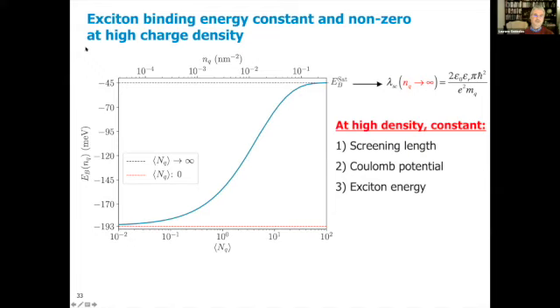And if you now calculate by solving the Schrödinger equation the exciton binding energy as a function of the number of charges in a nanosheet, you see that for a very small number of charges, or let's say when you go to zero, you get this 193, and that's what we put in here in the relative dielectric constant. And then if you increase the number of electrons and holes in a nanosheet, you end up at the saturation value of the exciton binding energy, which is minus 45 millielectron volts. So at high density for this two-dimensional system, we get a finite screening length. There is still a remaining finite Coulomb potential between the electron and holes. It becomes constant, and you get a constant exciton binding energy, which is not going to zero.